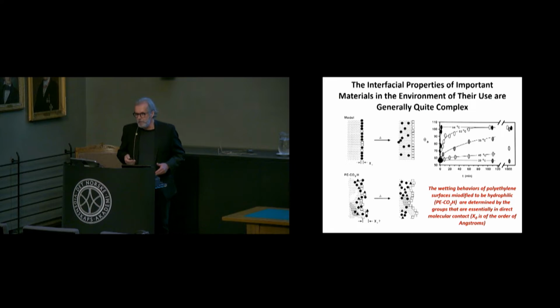And this is actually something that I can show you here in a little bit more detail in terms of the work that we actually did at MIT back in the late 70s looking at surface functionalized polymers. There's two pictures of substrates that embed certain levels of heterogeneity in what's present at the interface, shown as squares and black circles. And in particular, we have a surface modified polymer, which was a material that we had studied in some detail, the polymer being in this case polyethylene, chemically derivatized to be hydrophilic at its surface.